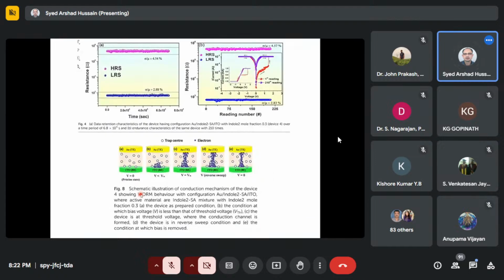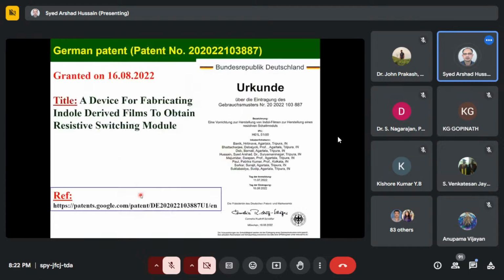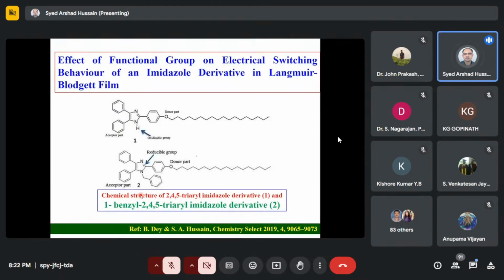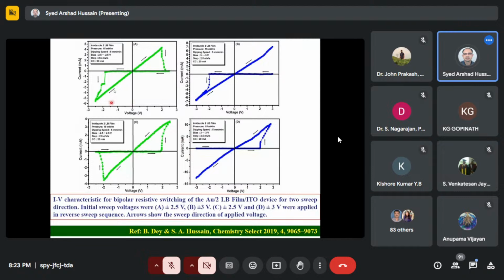Okay, so again we characterized the device, and we applied for a patent, and it's granted, on resistive switching using indole derivative. Then we analyzed the role of functional groups on resistive switching. We designed this molecule, an imidazole derivative, with this long chain with a donor, and we mixed it with stearic acid, and you can see initially it shows bipolar resistive switching.